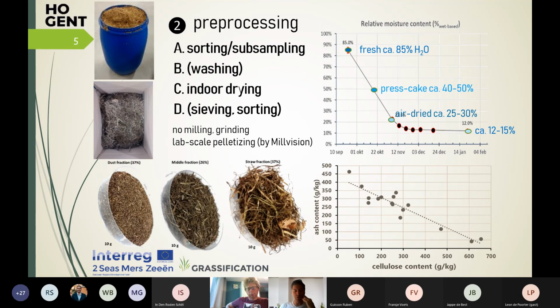One of the steps was also sieving. We wanted to look at the different fractions that were present in the grass supplied, and so we separated it in 3 fractions: the straw fraction, which are the longer and coarser fibers, then a middle fraction, which we call the pulp fraction, with short fibers up to a few centimeters, and finally the smallest fraction, which is a dust fraction containing organic and mineral material with fibers of less than 1 millimeter. So this gave us a range of raw materials which we analyzed chemically.